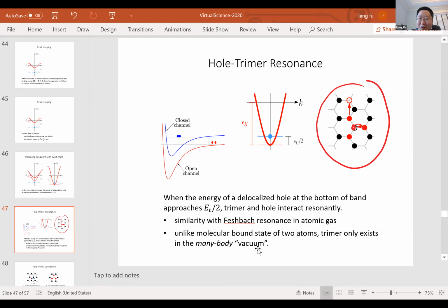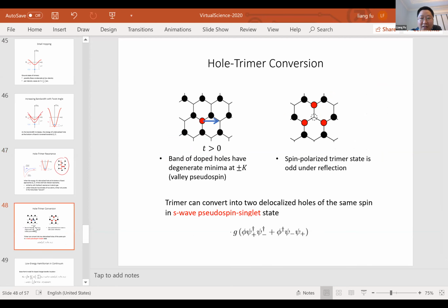Okay, so you take just two charges in free space, they always repel each other due to the Coulomb interaction. But the remarkable thing is that when we start with the charge transfer insulating state and add two actual holes, they can form a trimer, in the right parameter range.